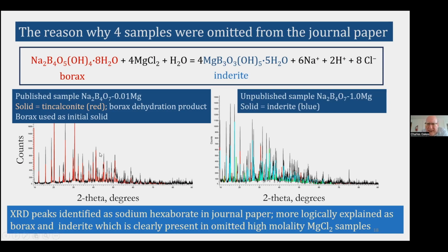So what this scan is showing is that the borax in the most dilute magnesium chloride solution remained as borax. Not surprising. Conversely, on the right here, we've got an X-ray diffraction scan of one of the samples at a higher magnesium chloride concentration.